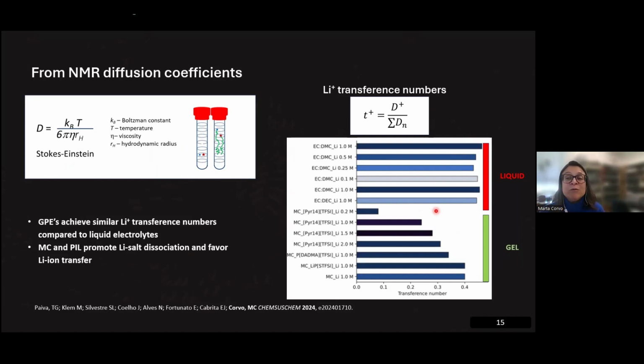What does this mean? This means that with this type of diffusion experiments, you can obtain the diffusion of each of the species, because it's dependent on the hydrodynamic radius of the species that is moving. Here you can see a pictorial view of what happens in this type of diffusion experiments with two different species. What we get is this behavior of decaying the signal as they are diffusing, moving in our solution, and we can relate this diffusion afterwards to the hydrodynamic radius of the moving species.